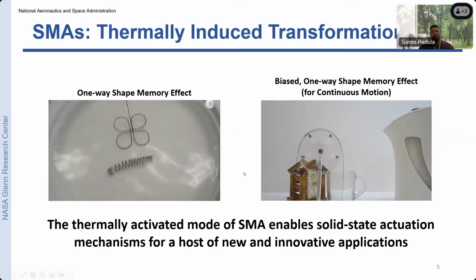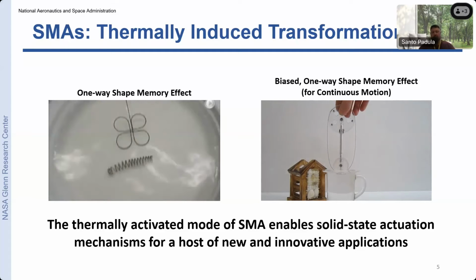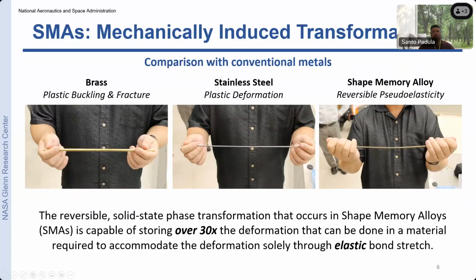In the other case, on the right, what we're going to be exhibiting is the utilization of this thermally induced shape recovery, where we take any type of heat source. In this case, we have a cup of hot water. And in any gradient field, we can actually create a mechanism where we can use the gradient field to create shape change and therefore produce continuous motion. So this mechanism opens up a whole host of other capabilities for the material.